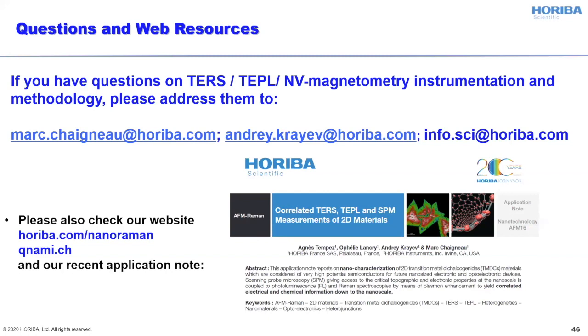So I understand where it comes from, but in tip-enhanced PL, or tip-enhanced Raman, we should remember that even if we have some in-plane components in the incoming field, the signal that we collect will be governed by the field which is perpendicular to the sample and which is pretty much along the TERS probe. The spatial resolution wise, I would say also it depends on the sample prep.